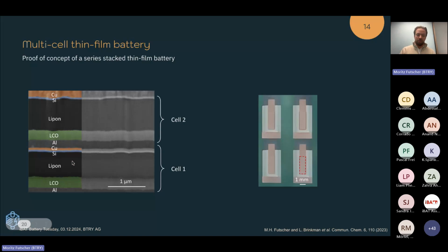We have the LiPON as a solid-state electrolyte. In this case, silicon as an anode and copper as a current collector. And then repeat this again to really have the second cell on top of each other. And here you already see why vacuum coating is important here. We have here quite a lot of layers on top of each other. And these layers are very thin. So we need really high precision fabrication methods to enable several cells on top of each other with a high yield.